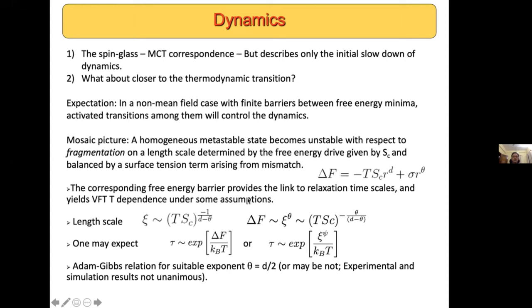And in the usual way, one can then ask what is the location and size of the free energy barrier, and the location is given in terms of a certain length, which from the form of the free energy cost for any droplet of a certain size is the configurational entropy to the power of -1 over d minus theta, and the free energy cost would correspondingly be the entropy to the power of minus theta over d minus theta.